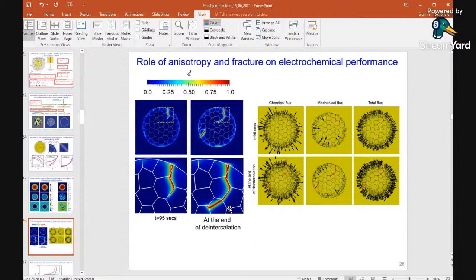The crack will try to enter mostly on the radial side, even if there is a grain boundary. If the grain boundary assists it to enter in the radial direction, that's fine. Otherwise, it will try to enter through the crystal itself if the crystal is weak in a particular direction. So we have anisotropic energies, and all the anisotropies are taken into the picture. Now the right hand side figure shows how the crack is developed, how the flux is developed.